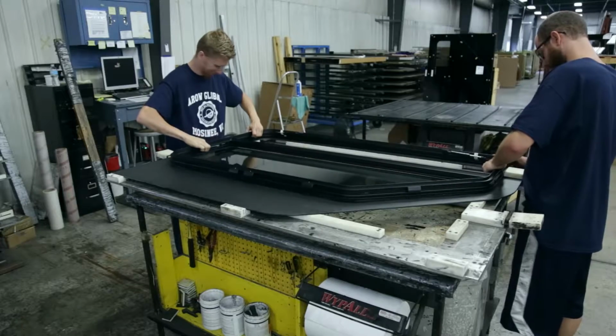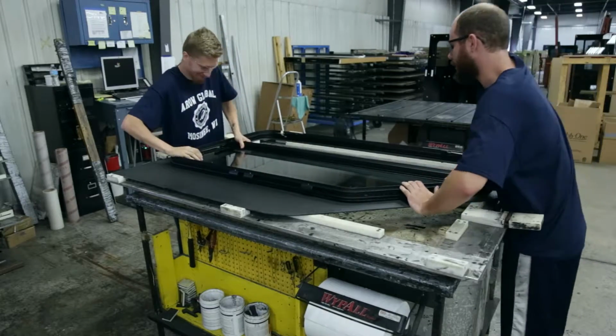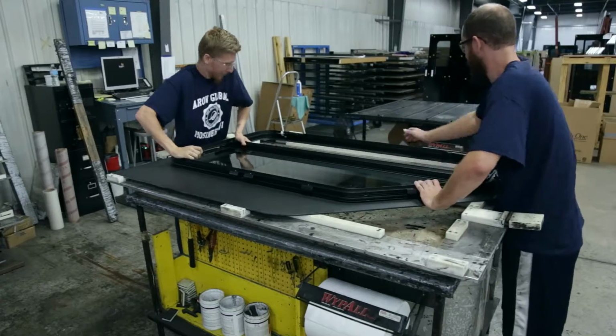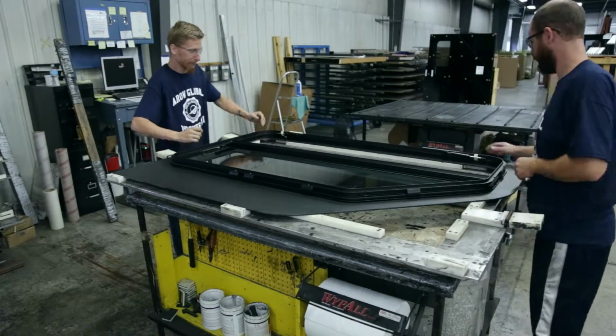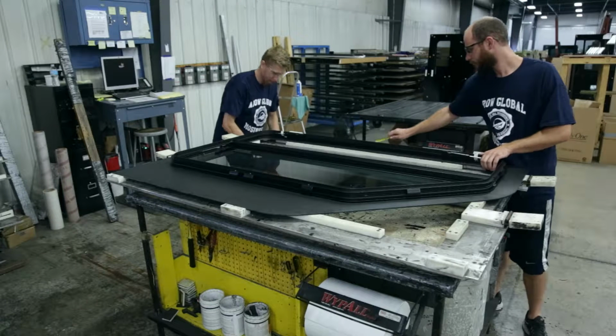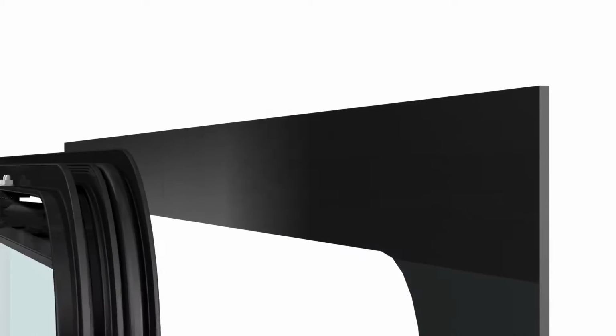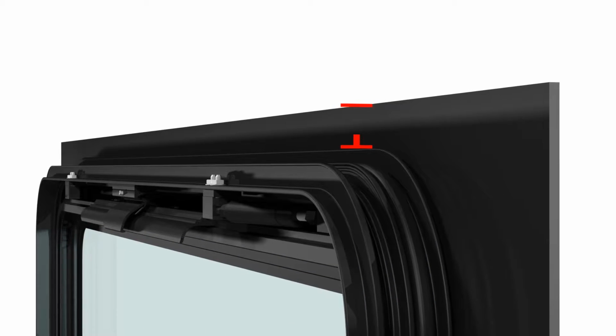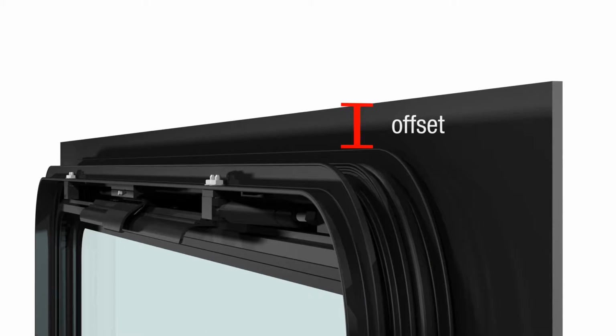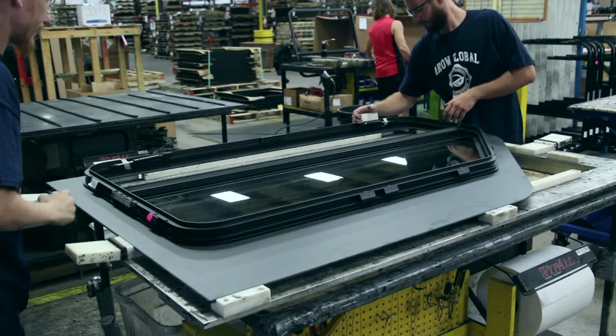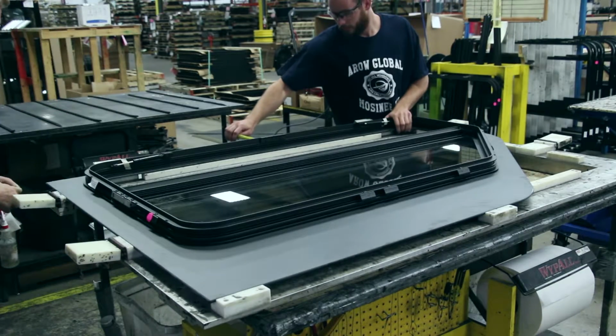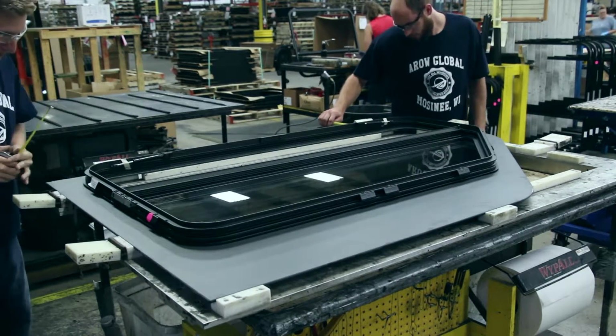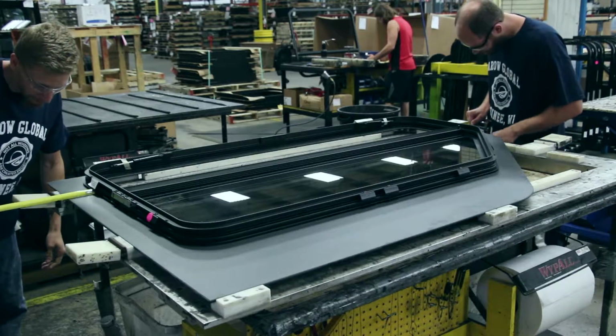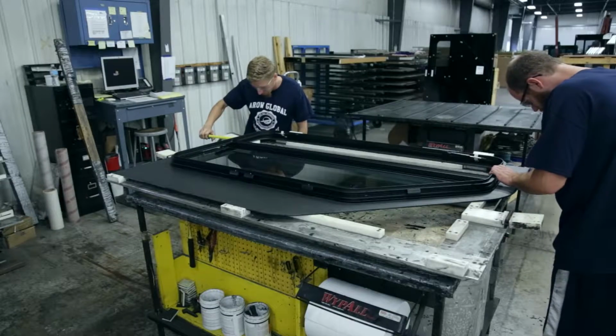Step 7. There is a 10-minute maximum time limit from the time you start applying the adhesive to the time the frame or hinge is set onto the glass. If this is not completed within the time limit, the adhesive must be removed and the procedure will have to start over. When locating the frame on the glass, the offset between the top edge of the glass and the frame is a critical dimension and must be maintained as specified. If this dimension is not maintained, it will result in difficulties closing the window. Place the frame onto the glass and use the measuring tape to ensure the proper offset between the frame and the edge of the glass is achieved. The lip on the window frame should contact the glass when the frame is fully set in place.